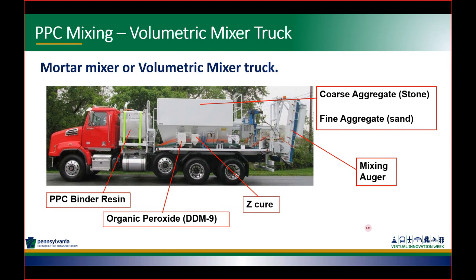So this truck was specifically developed for mixing polyester polymer concrete, and we have a large tank that stores the resin, the polyester polymer resin, and then we have two smaller tanks that hold the DDM-9 and the Z cure. Also in the truck, there are two bins that hold the aggregate. So the aggregates are separate, fine and coarse. They are separate, and the conveyor belt brings the aggregate to the back of the truck. At that point, all the components are supplied and they are mixed in an auger.